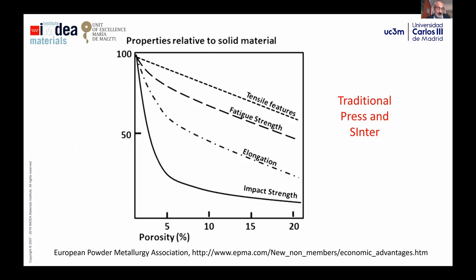And the negative part of this kind of production method is that we tend to produce parts with a lot of porosity. And porosity decreases most of the properties a lot. Of course, the tensile features decrease in a linear way, but if we go to properties linked to the ductility of the material, such as elongation or impact strength, the properties decrease in an exponential way. With just 5% of porosity in a part, we can lose more than 50% of the final property of the material. So that is the typical conventional powder metallurgy, in which we have a low-cost part with enough properties for the application, but with much worse properties than conventional ingot metallurgy or wrought metallurgy.